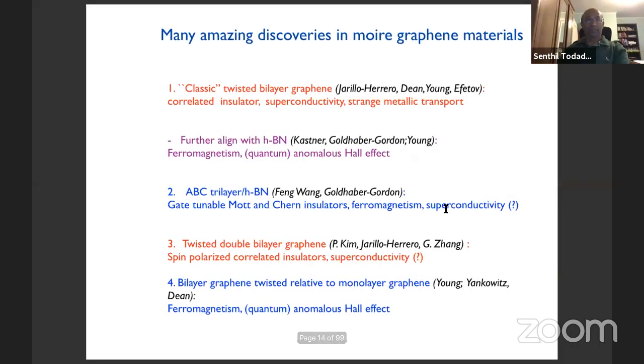Okay, so there's many kinds of amazing things that have been discovered in the last 2.5 years in this field. In the original twisted bilayer graphene, the experiments that I already mentioned show the correlated insulator and superconductivity. If I have time, I might show a slide on some weird metallic transport that has been observed. Now, if you take this magic angle twisted bilayer graphene and you align one of the two graphene layers with a hexagonal boron nitride substrate, that system has been studied, and it does something very interesting.